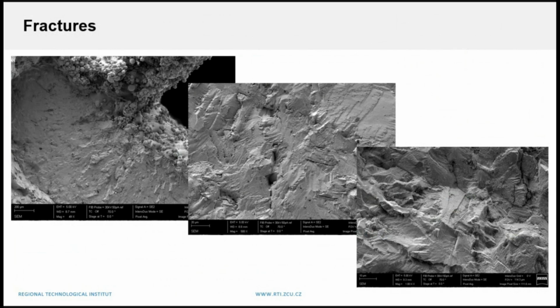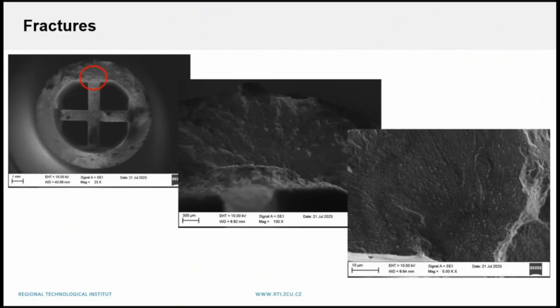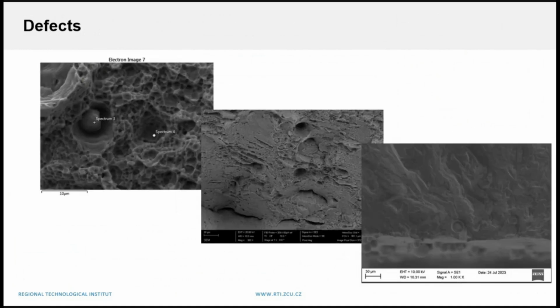And in this area, there are good potentials for cracks. When we check it a little deeper in this area, we could see that there is a lot of lack of fusion. There are holes where the insides are non-melted materials, and this is big trouble in this area of fatigue, because this is a nice concentrator of cracks, of course.